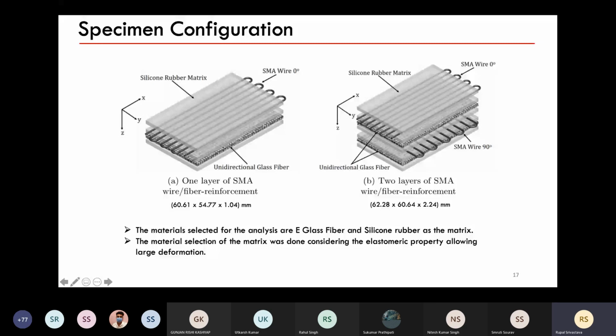In the second structure, because we also wanted a bimorph, and we are talking about a torus-like structure, we need a very curved structure. We do not need just one direction of bending. So we embedded our shape memory wires in 2 layers, orthogonal to each other. When this layer shrinks, it is going to bend the structure in one direction, and when this layer shrinks, it is going to bend the structure in the other direction.